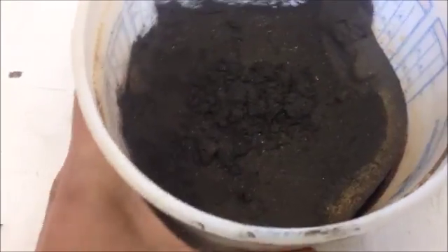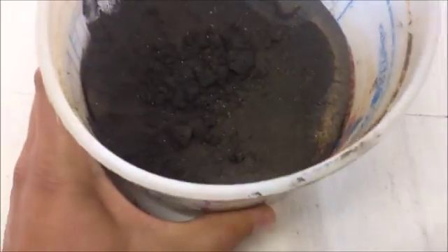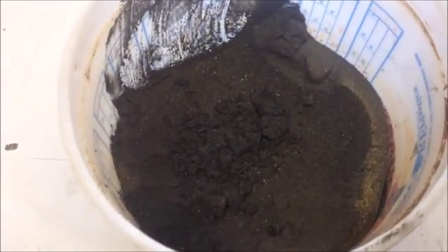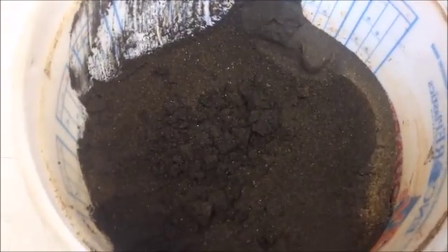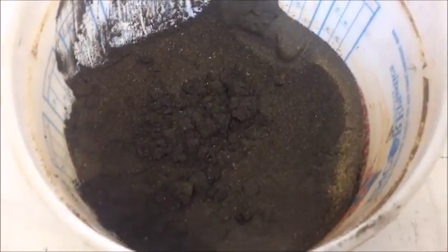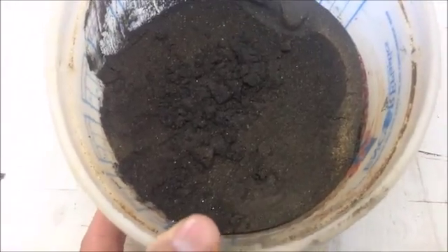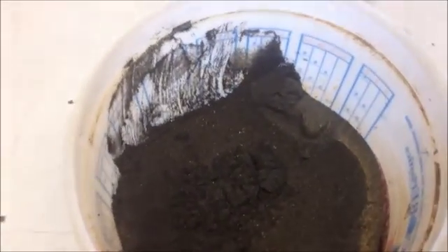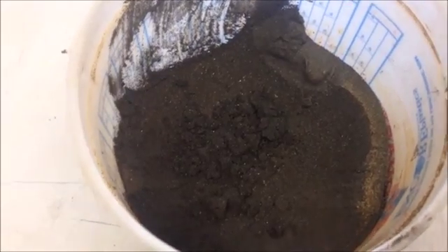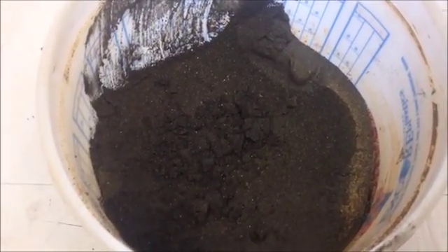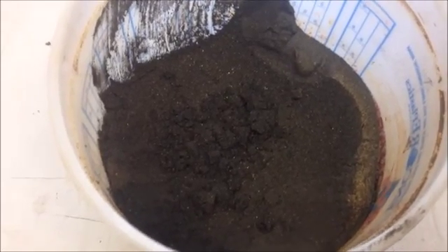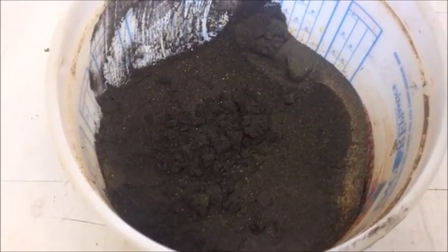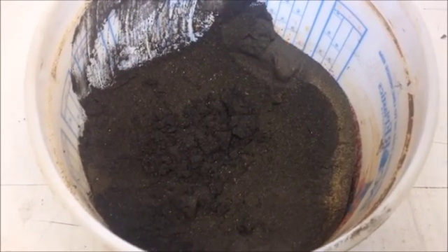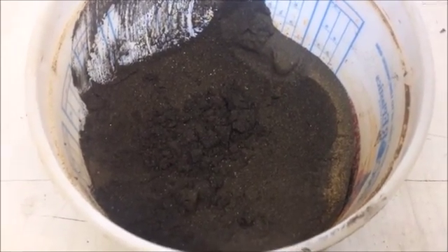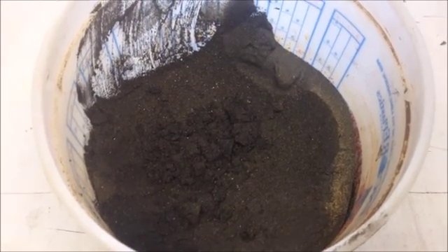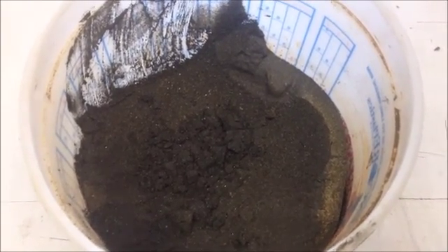But the reason I'm doing that is because it's really hard to roast a bunch of material. It's fairly easy to roast about a quarter cup or half a cup. But when you want to do pounds and pounds of material, it actually takes a really long time, and you've got to have it all exposed to the oxygen in the air, and you've got to get it to about 12 or 1300 degrees Fahrenheit. So I'm going to try and force it into a matte phase through the first smelt, and then after the first smelt, I'm going to take the matte and reprocess it using potassium nitrate, which is a very extreme oxidizer, and some iron filings, so I can avoid the roast.